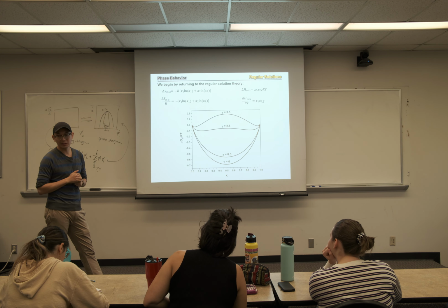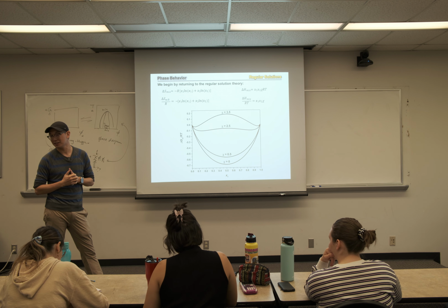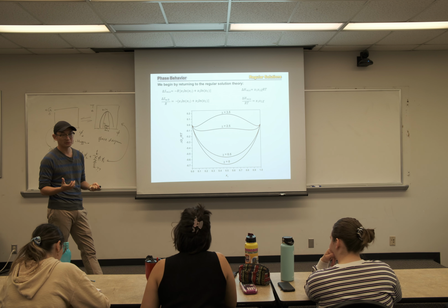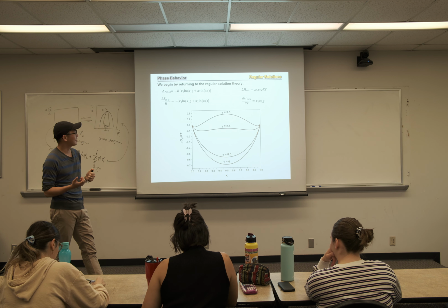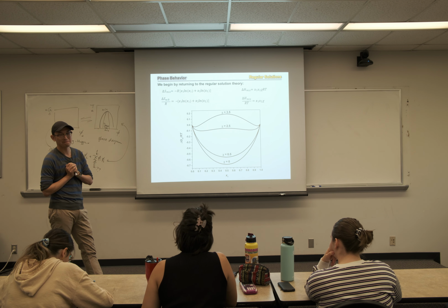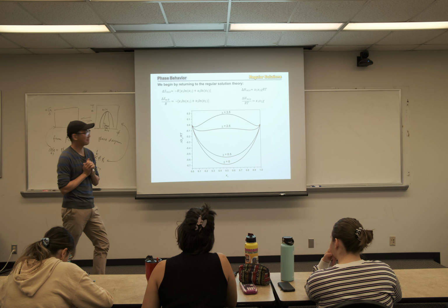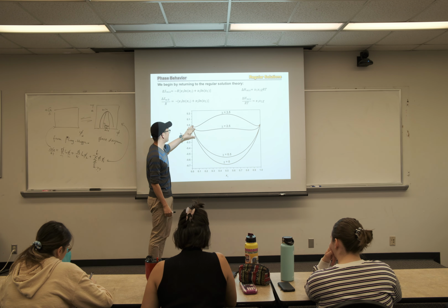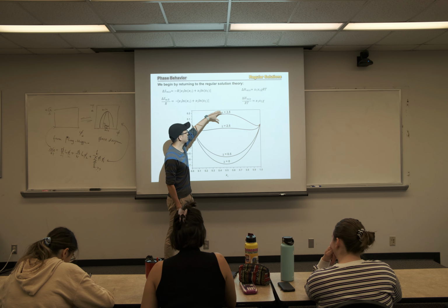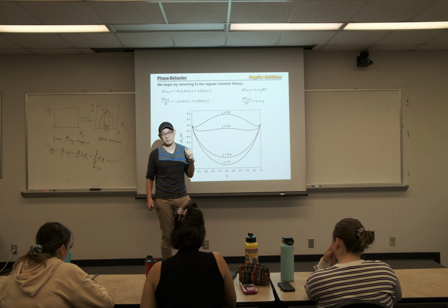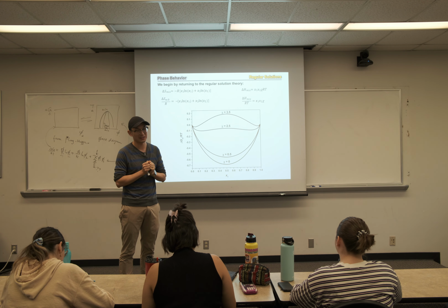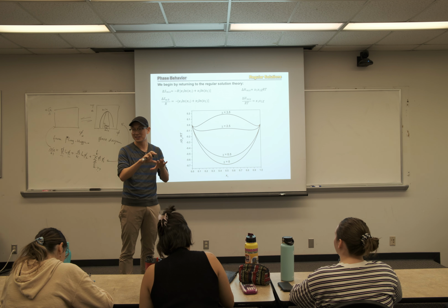One of the important conclusions we reached in the last lecture is that to determine if your solution will be stable or not stable, we need to take a second derivative of delta G with respect to phi. That will tell you the sign of the local shape of this curve, delta G. If your delta G is concave down, that means it will not be stable. Your polymer solution will choose to phase separate into two layers.